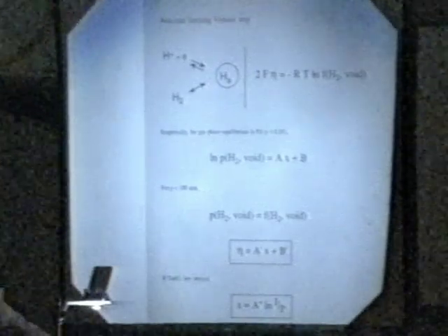Are there any data to support such a result? In fact, there are. We have some data ourselves at SRI, but I forgot to bring them with me. It may actually be a blessing, because I can now show the data of another group. This is the Komatsu group in Sapporo, a paper presented at the Nagoya meeting, where he carefully sets out to measure loading versus overvoltage and versus the log of the current, more or less in the range I was talking about. And you see a fairly nice linear relationship.